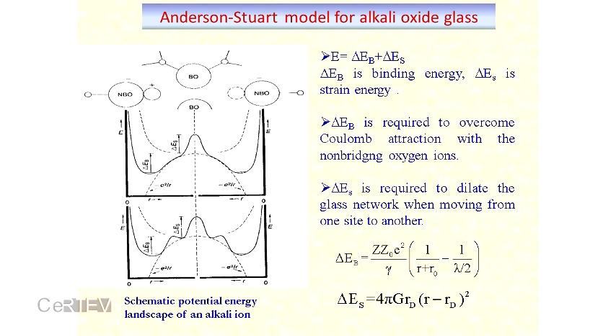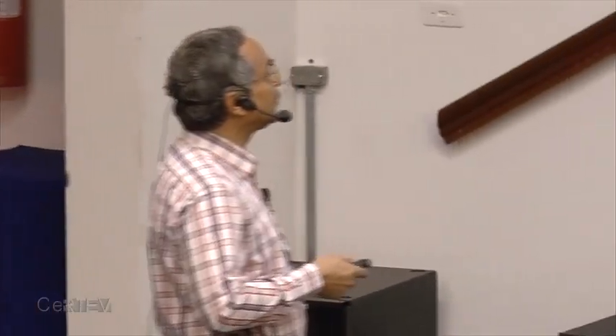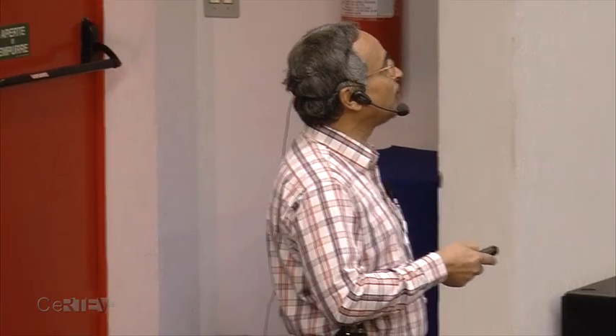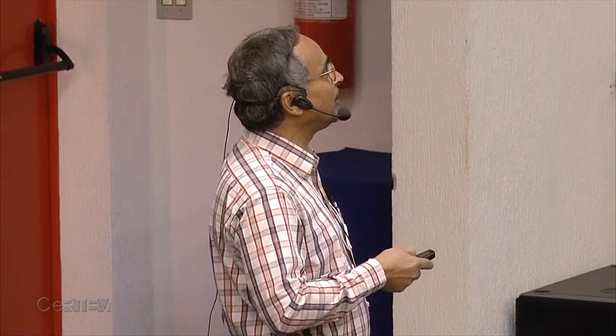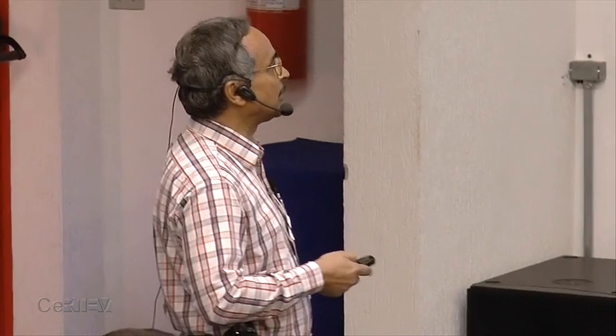So the total activation energy for hopping from this side to this side, the barrier, consists of two parts. One is the binding energy, the other is the strain energy. Theoretically, the Anderson and Stuart model calculated it in this way, and we have also calculated it for various materials. It is shown here, the potential energy landscape before the ion is there, and the change in the landscape when the ion hops from this side to that side.